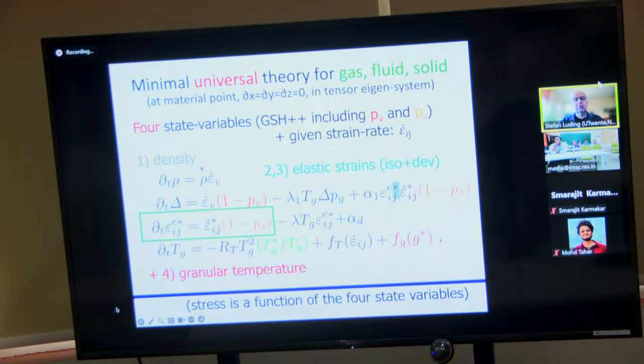This is how the evolution equations look. The time derivative of density is proportional to the isotropic strain rate and the density. That's mass conservation. This corresponds to the isotropic stress evolution. Here we write it as isotropic strain evolution, and it's proportional to the isotropic strain rate times 1, that's the elastic part, minus the possibility for plastic events. So the 1 stands for elastic, the PV stands for plastic.